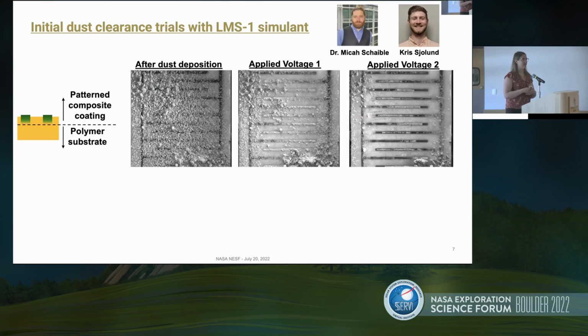And then again, in collaboration with Dr. Micah Schaible and our collaborator, Kris Sjolund, we looked at how these devices clear dust from the substrates. You can see after dust deposition, we've got pretty good coverage on the device. Then as we apply a low voltage, we get fairly good dust clearance. And as we increase the voltage, we get additionally better dust clearance. This was really encouraging because these are as-produced devices, so no additional processing needed.